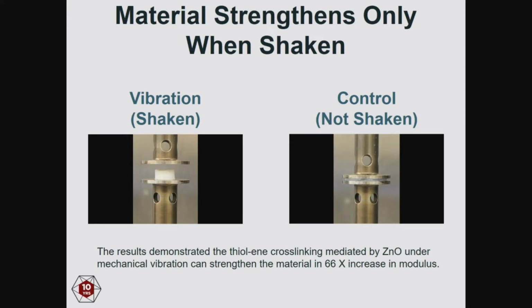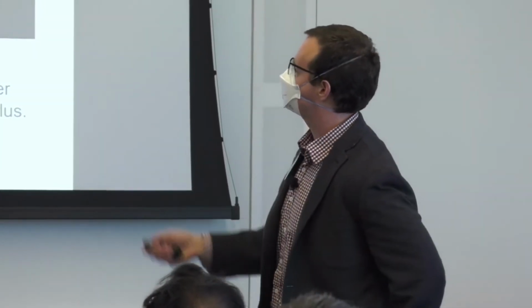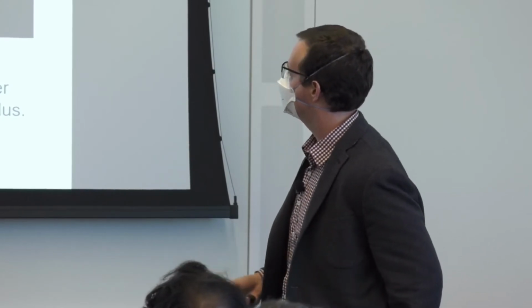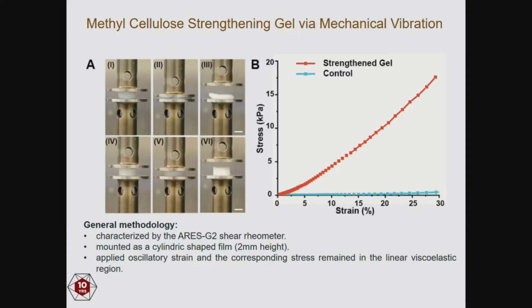And so this is the difference, that we start with this very soft and squishy material. When we shake it, it gets stronger over time. So literally, we're hitting it with thousands of tiny little micro vibrations, and it's getting stronger and stronger as we do that. And we can measure that using rheometry. And this is the overall increase in stress. And in fact, it gets 66 times stronger. It started out very, very weak. So that's a large improvement. But we started from a very low number. And that's what we demonstrated in this paper, that we could make this material that was able to strengthen itself by harnessing the energy around it from its environment.